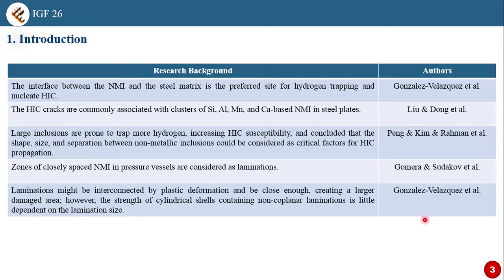Gomera and Sudakov claim that zones of closely spaced non-metallic inclusions in pressure vessels are considered as laminations, and González-Velázquez also reported that laminations may be interconnected by plastic deformation and be close enough that they create a large damage area.